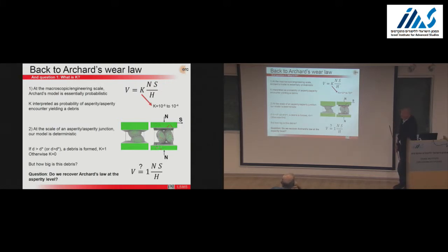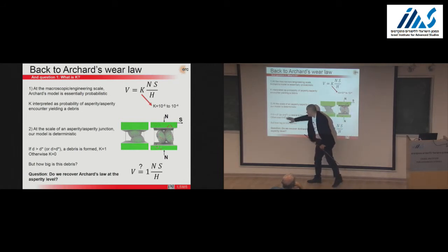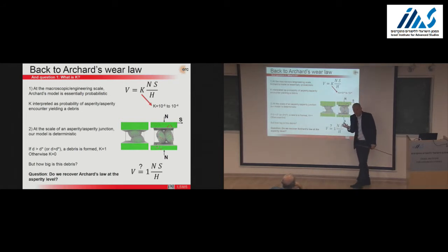Okay, back to Archard wear law. I want to go back to this definition of K, which remains a mystery. So K is the small number interpreted as a probability of junctions forming debris. But now suddenly we become deterministic for K. Because what I told you so far is that there's this critical length scale or critical area of a junction above which you form a debris. So if your microcontact is too small, K is equal to 0 at the level of this microcontact. But if your microcontact is big, K is equal to 1.